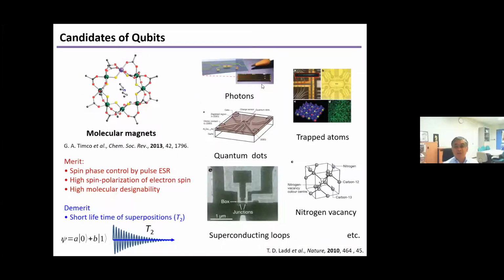So there are some qubit candidates: photons, quantum dots, superconducting loops, trapped atoms, and nitrogen vacancy. But now molecular magnetism is very promising. The merit of molecular magnetism is that spin phase can be controlled by pulse EPR, there is high spin polarization of electron spin, and high molecular designability. But the demerit is the short lifetime of superposition, T2, the spin-spin relaxation time. So this is a demerit.